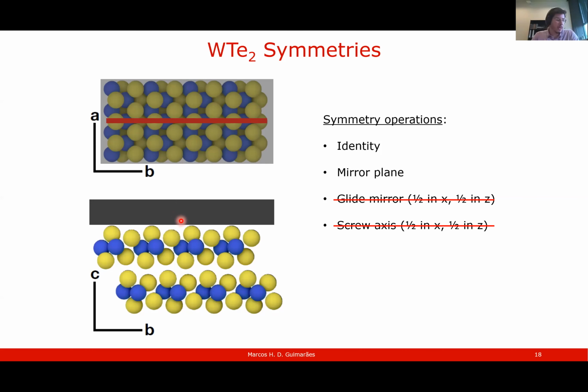But in principle, you don't need to have this permalloy actually to measure something that is similar to what we measured in tungsten ditelluride. And this was shown by Pablo Jarillo-Herrero and Kin Fai Mak last year, if I recall correctly. They showed the nonlinear Hall effect in tungsten ditelluride, and this is consistent with what we measure here. I see. And then also the fluctuations from one device to another could probably be explained by this, no? The quality of the interface should very strongly affect what you see, right?